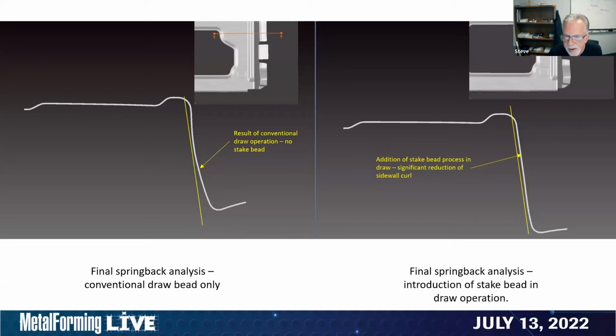Yep. On the left is the result of a conventional draw operation. That's just a conventional bead. This is a final spring back analysis. This is actually done in AutoForm. And you can see the curl, the resultant curl along that vertical wall. And then on the right is the addition of a stake bead process in the draw. You can see the reduction, the difference in the amount of curl. That yellow line represents a straight line. Both of these were performed in AutoForm, and we have pretty solid correlation between these results and some test tools that we've built at Diversified Tooling, and some actual production tools as well. So you can see the benefits of using something like a stake bead in your process.